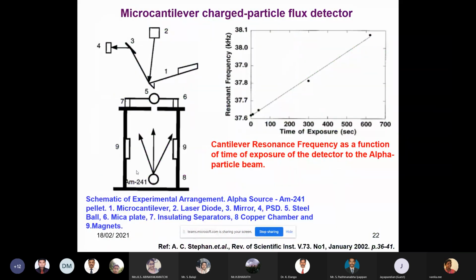Then we checked the composition of the cantilever. For that we did SEM analysis. Then we found the aluminum and silicon combination that gives the bimaterial nature and acts like a calorimetric application, like a temperature difference. That is why we are able to get a slow variation in the exposure of UV light switching on and switching off. This is one interesting result.